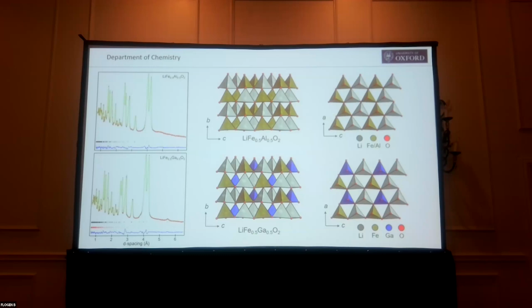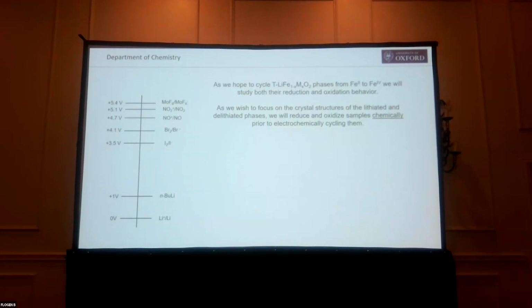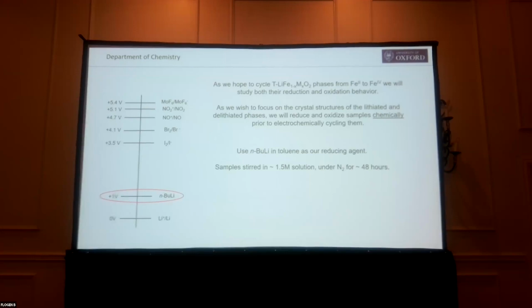Because we're interested in the structure, we're interested in the fundamentals of these materials rather than the cycling, what we're going to do is the redox chemistry. We're not going to do it electrochemically, because if you then have to recover the material from the electrochemical cell, it really compromises your structure. So here are our oxidizing and reducing agents. We're going to start off by looking at the reduction, and we're going to use butyl lithium as our reducer. So we take our oxide materials, stir them up in hexane for a couple of days, and then filter them and see what happens.